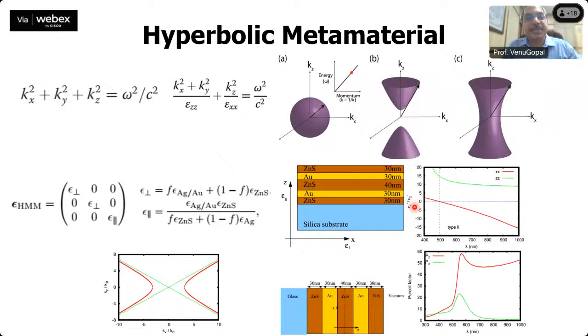Right. So I mentioned these anisotropic materials. I'll show one consequence of this. This is a hyperbolic metamaterial. Right. So here, as I mentioned, it's no longer an isotropic spherical dispersion profile, but you can have epsilon xx and epsilon zz to be different. So they can be negative or positive. So depending on that, you can have different dispersion profiles where very high K vectors are also possible modes within this material.